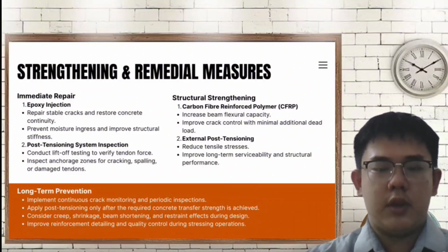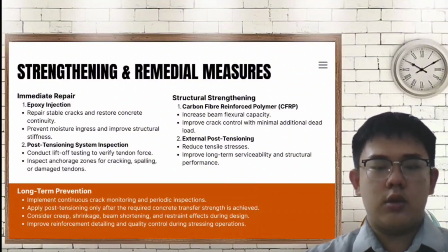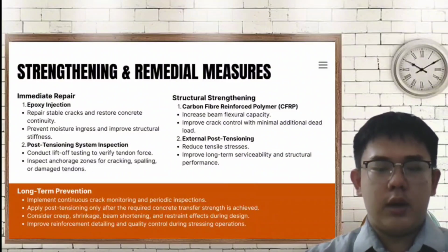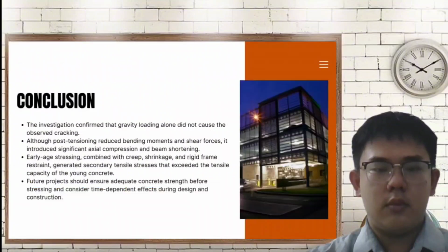Post-tensioning should only be carried out after the concrete has reached the required transfer strength. During design, engineers should also consider creep, shrinkage, beam shortening, and restraint effects. In addition, proper reinforcement detailing and strict quality control during stressing operations are essential to prevent similar problems in the future. In conclusion, this investigation confirmed that gravity loading alone was not responsible for the observed cracking.